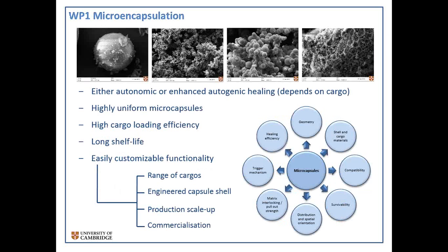So first of all, what University of Cambridge are looking at is microcapsules. On the top of this slide you can see the early stage images of the microcapsules. These are very small polymer or synthetic capsules which can contain a number of different cargoes which are healing agents. They can be used to heal the cracks in concrete. So the idea is to create these capsules and then mix them into the concrete, and then when cracking occurs, the crack either forms through the microcapsule itself, or there is a release mechanism for the healing agent, which then releases and glues the crack faces back together essentially.